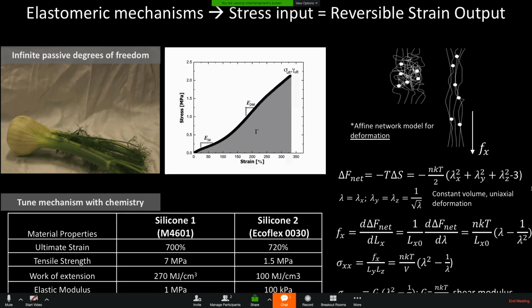The reason it comes back is due to entropy. These are entropy-driven systems, a polymer network. So you take out enthalpy from the equation, and the free energy equation, if you take the derivative of the entropy with respect to length in the uniaxial direction, and you just go through this, then you get the force per extension. And if you take that force per extension by the area, then you get the stress. And that stress is proportional to G. G is the elastic modulus, which is represented in that curve.